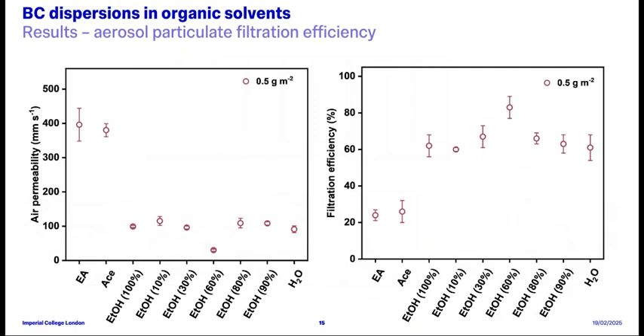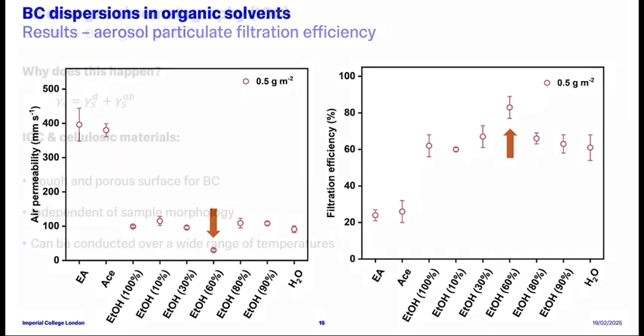So this difference in bacterial cellulose coverage is further supported by the filtration properties result, where the bacterial cellulose coating applied from a 60% ethanol-water mixture has the highest filtration efficiency, inferring that there is a better dispersion of bacterial cellulose in ethanol-water mixture than water, which results in a more homogeneous coating. But the question remains as to why we are observing this and why would this happen?